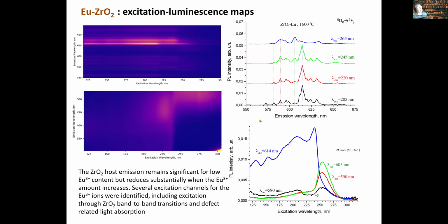Additional possibility to check crystalline quality of the material is to dope with some markers. Actually, europium ions are really very good for using as a marker of the crystalline structure because their emission is sensitive to the crystalline field. And for our case, we use a very low amount of europium to see whether we're able to excite these rare earth ions through excitation through matrix absorption or band-to-band absorption.